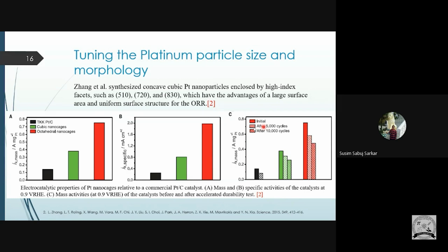And this is the mass activity reduction after 5,000 cycles and 10,000 cycles, whereas the normal platinum electrode is so much reduced after 5,000 cycles, and after 10,000 cycles we can't get any measurable amount. So in that case, if we use the octahedral nano cages, after 10,000 cycles it is still higher than the cubic nano cage, and obviously higher than the normal platinum carbon electrode.